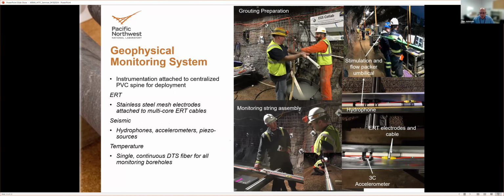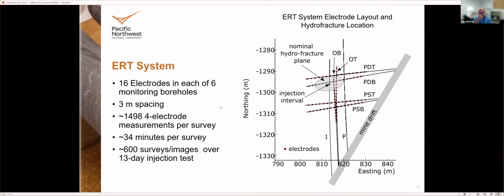So this is just some quick images of what our instrumentation strings in the grouted monitoring wells look like. Here are some pictures of us installing them. We had hydrophones, everything was in, and the ERT electrodes are shown here. The electrodes were just a stainless steel mesh that were strapped to a PVC spine. And then we inserted everything into the borehole and grouted it in place, hoping that the grout seal would protect all of the equipment from the high pressures and that it wouldn't leak, and that didn't turn out to be the case at all. That was a lesson learned. But there were some consequences of that in terms of the ERT images that I'll show you shortly.